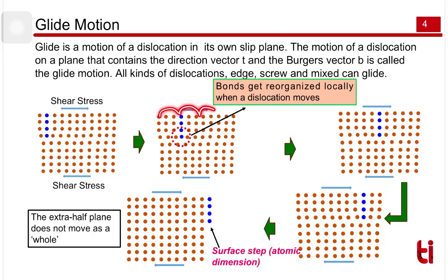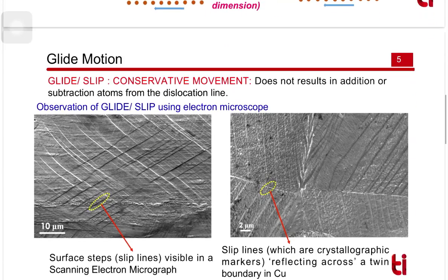So here this dislocation is moving step by step, and finally it comes onto the surface. Once it comes to the surface, this becomes a perfect crystal, and this is no more a dislocation, but a step on the surface. As written before, it could be restricted at grain boundaries or at free surfaces. So this motion we call the glide motion.